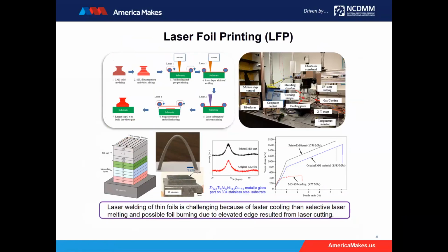And we also developed a process called laser foil printing, which is essentially a layered process where you laminate, right? Like a laminate manufacturer, you laminate from one metal foil to another, but you cannot simply laminate because it's difficult to bond them together. So what we do is spot welding, and then continuous laser to do pattern welding. So you weld the top layer to the bottom layer, but then you go through a cutting process using the pulse laser so that you can cut every cross-section with the right contour.